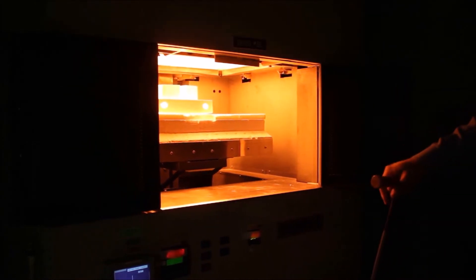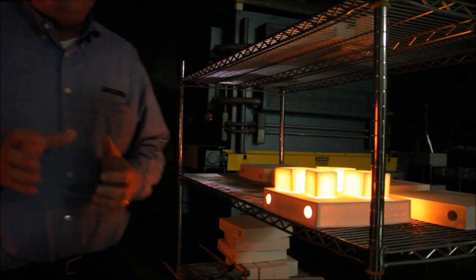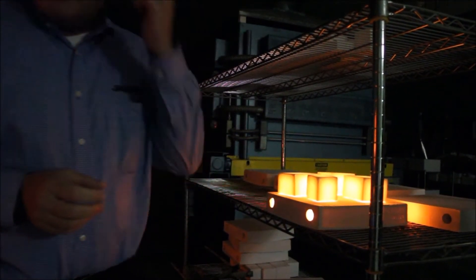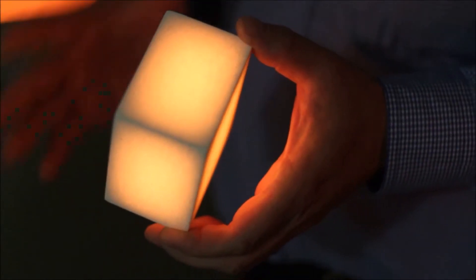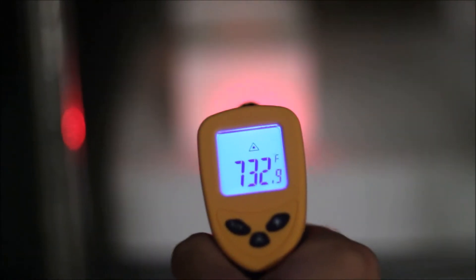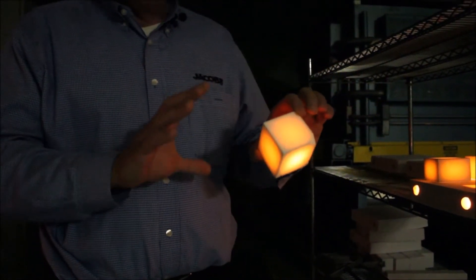While at the facility, Martin demonstrated how some of these materials actually work by taking them out of a kiln. What I'm going to show you here is a little bit of a trick — a good demonstration of some of the properties. These materials are made fundamentally of silicon dioxide, of silica, which is an incredible material. It has a very low thermal conductivity and an extremely low specific heat, so it doesn't conduct heat very well. That allows you to pick up these coupons just a fraction of a second after they're brought out of the kiln. The core of this is still well over 2,000 degrees, but the corners and edges have cooled off enough that I can handle it without burning myself. This is actually about 94% air and 6% solid phase, and because of the low conductivity, the core of it will stay hot for quite a long time.